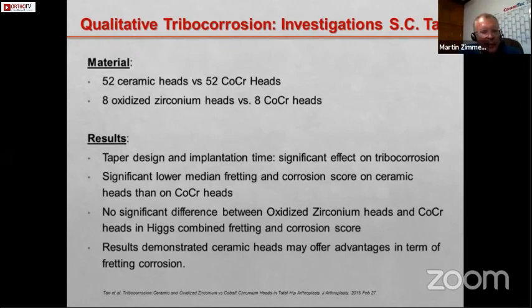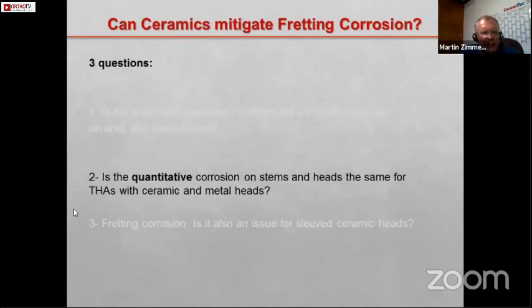Anyway, they came to the conclusion that the taper design, specifically the taper size and the implantation time, has a significant effect on fretting corrosion. That means the longer you have the hip in vivo, the higher the risk of fretting corrosion, and the smaller the taper size, the higher the risk, because you have a higher torque acting on the taper of the stem coming from the ball heads. For the first group, they found clearly there was a significantly lower median fretting and corrosion score on the ceramic heads than cobalt chrome. In the second group, between the zirconium and cobalt chrome, there were still no differences between the two groups. And finally, they came to the conclusion that using ceramic heads may offer advantages in terms of fretting and corrosion. Let me go now to the second aspect. What about the quantitative corrosion? From where does it come?